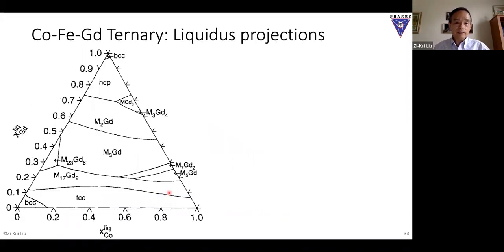Now, in terms of liquidus projection, usually when you talk about liquidus projection, you project to the composition triangle. So you have temperature projected to the composition, and you get the cobalt composition and gadolinium composition here. So you see there's a BCC phase region, FCC phase region, and different compounds, and the BCC plus liquid region there. So you see this kind of liquidus projection. However, this one only gives out the phase region, so it's very difficult for us to see temperature.